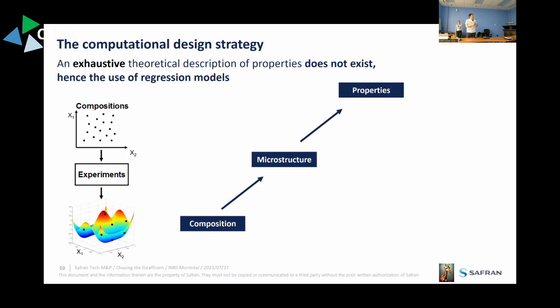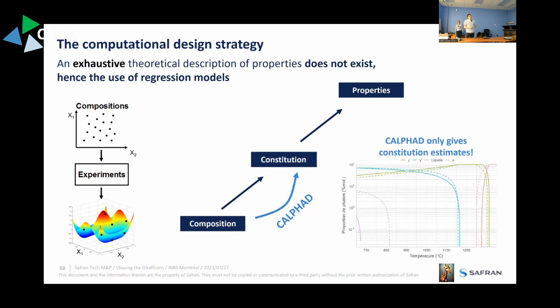So the design strategy, I'm going to go over rather fast. The idea is that usual triptych. What we did was not link composition to microstructure, but we used CALPHAD, so calculation of phase diagram methods, to get information about the constitution. There's no geometrical aspect to this prediction. It gives you the evolution as a function of temperature of the phase fractions, and it allows you to see if a composition is a gamma prime alloy or if it contains other phases that you don't want to have. And then, as I said before, the idea is that we don't really know how to go from there to there with physical models, with a full chain of physically informed models.